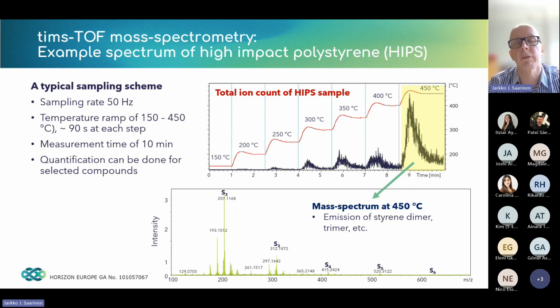On the top image here, we have the total ion count of the high impact polystyrene. We do see that once we increase the temperature, the total ion count is increased as the thermal degradation starts to play a role. And from each of these different points, as we collect the data, we can take a look at the mass spectrum distribution of different compounds that are emitted at these different temperature points. So here, as an example, is an example of the 450 C emission.